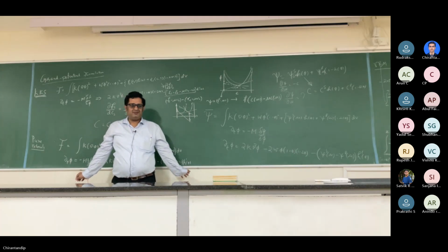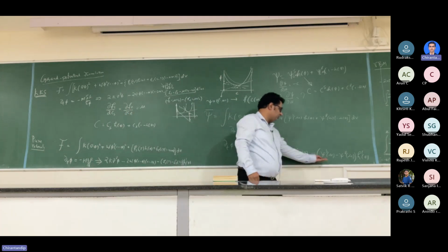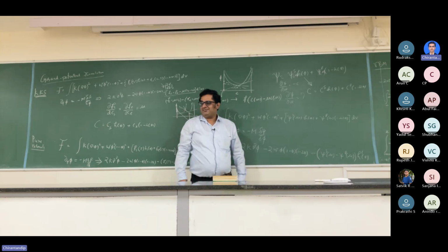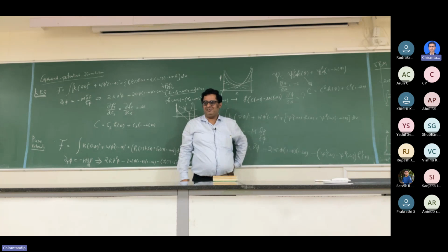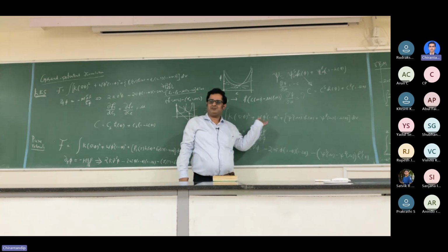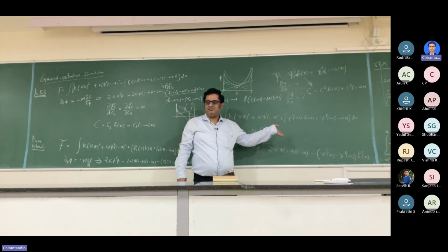Agree? So what is the expansion of this? Minus fl minus mu cl times h prime of phi. This is what your KKS model was, right? But it came down in one step. So they started from a different functional. Okay? Magic, right? Just for a change of variable.